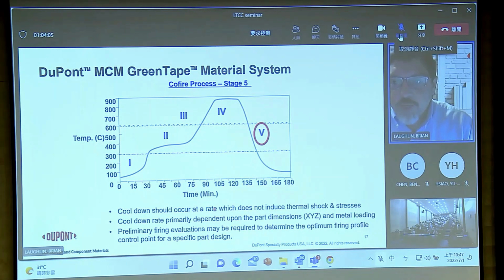And then the final step, it's usually not particularly critical as long as you don't cool too fast. So you do have a ceramic material at the end, probably coming from the high temperature state. You need to cool relatively gently up to some point so you don't thermally shock and cause micro cracking or even massive mechanical failure of your part. So you have to avoid thermal shock. So the cooling still needs to be considered in your full firing process.